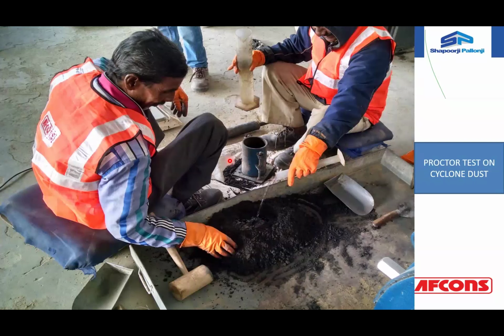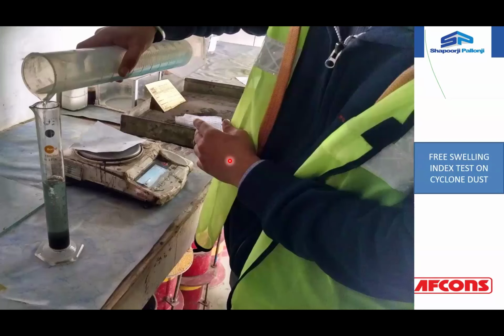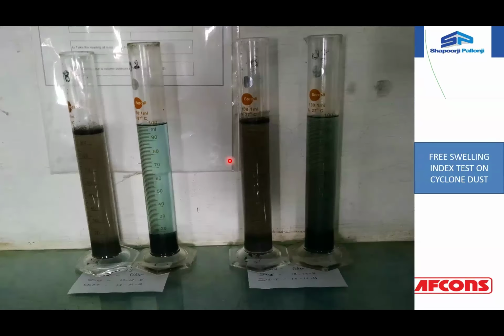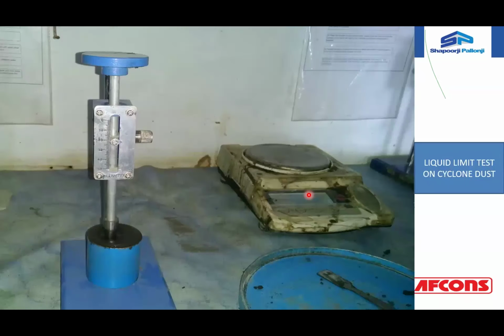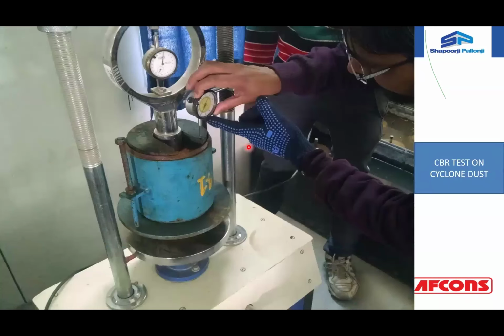Now, the idea is to test the material for the different properties which are given by MORTH. Like we started with the Proctor test, the density test, and then the free swelling index using 2720 part 40. And then you can do the liquid limit test by cone penetrometer, and of course the CBR test of the cyclone dust. The beauty is, any material you want to use in any layer of the road construction, you need to first check its suitability based on requirements given by MORTH.